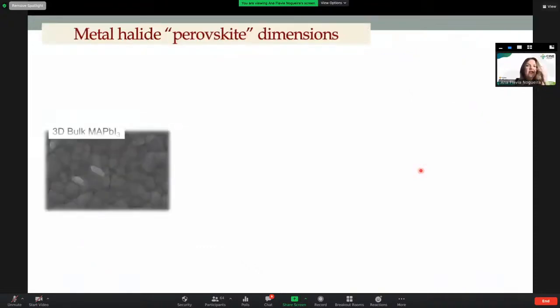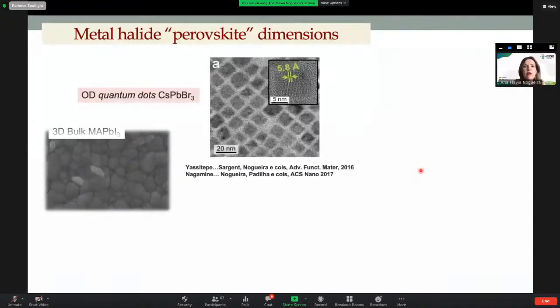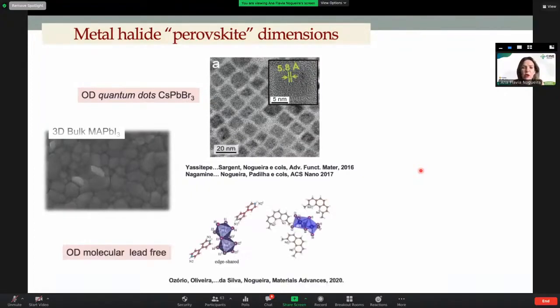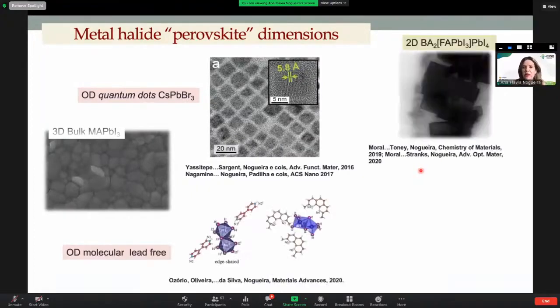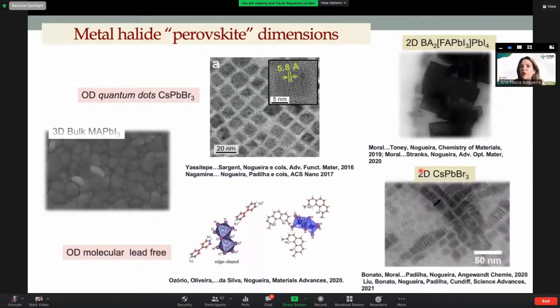Also, you can make these metal halide perovskites in many different dimensions. This is an example of an SEM image of the traditional MAPI film that is used in photovoltaics. It's 3D. But we can also go to perovskite quantum dots. This is an example of cesium lead bromide, which we use for light emitting diodes, for instance. You can have molecular lead-free perovskites, and also 2D. For the 2D perovskites, you can make them large, in micron size, and also decrease down to nanometers, like nanoplates of these perovskites. These 2D materials are very interesting for light emitting applications.